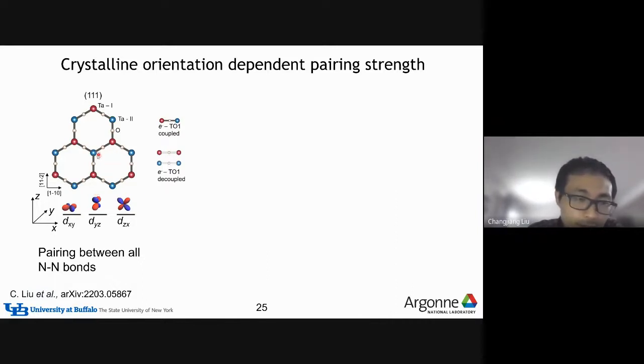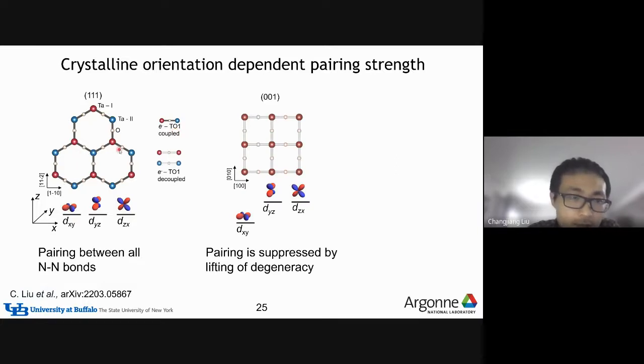And further, you see that for the KTO-111 surface, adjacent tantalum atoms are from two different layers. Basically, the red and the blue color represents the two layers, and we found that the TO1 phonon can couple adjacent layers of d orbitals in the tantalum site very effectively. However, if the tantalum sites are in the same layer, just because of the symmetry, the TO1 phonon coupling is very small. So now for the 001 surface, all the tantalum sites are on the same layer, I mean the adjacent tantalum sites are from the same layer. So the TO1 phonon coupling is very small.